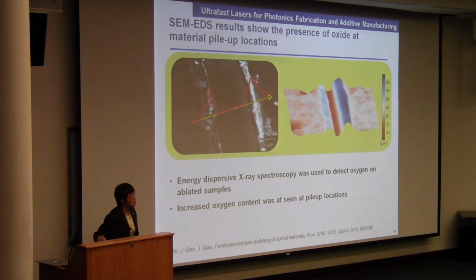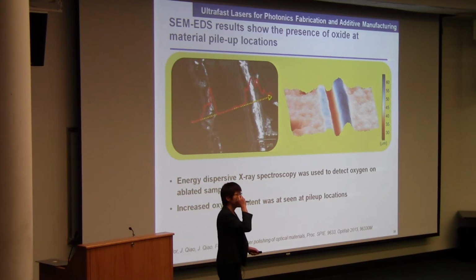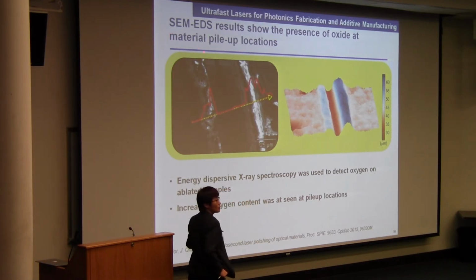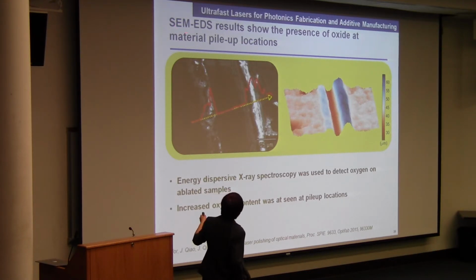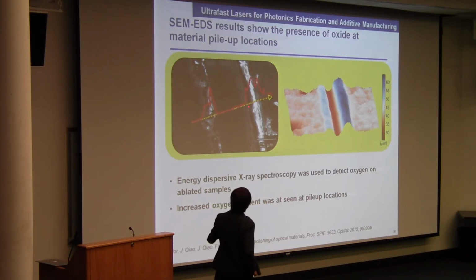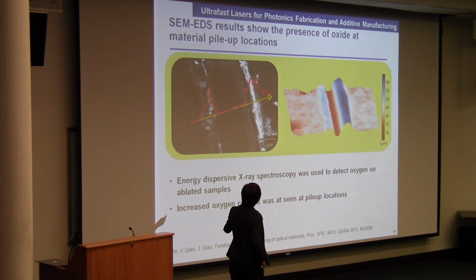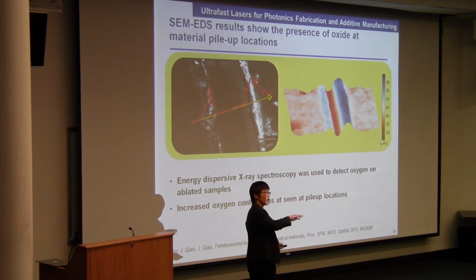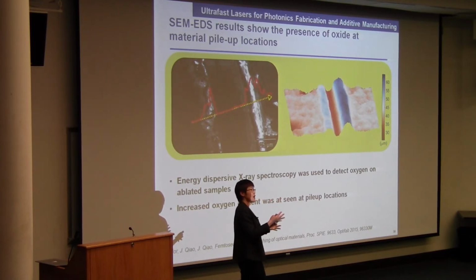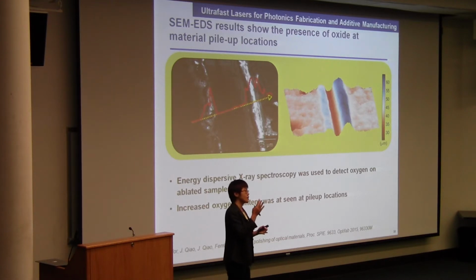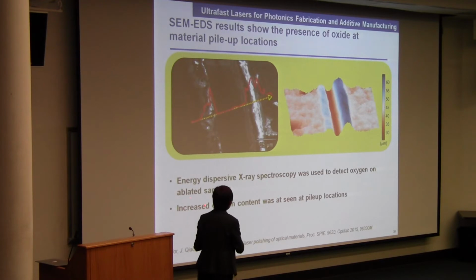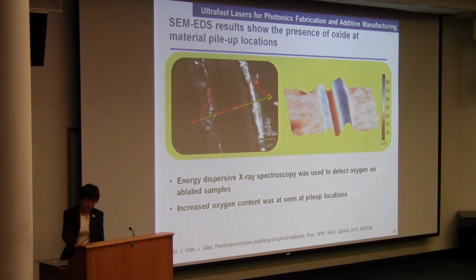So now the material aspect comes to play. I have a visiting scientist, Jie Qiao, and he is in material science. So we were able to use, working with Professor Rich Hilton, SEM EDS measurement that show the presence of oxide. By measuring the spectrum of material, we were able to compare the processed area with the unprocessed area, which shows an increased peak for oxide. So we know there's oxidation occurring, but we also suspect there is material melting as well. The technique was energy dispersive X-ray spectroscopy, and we verified the oxidation.